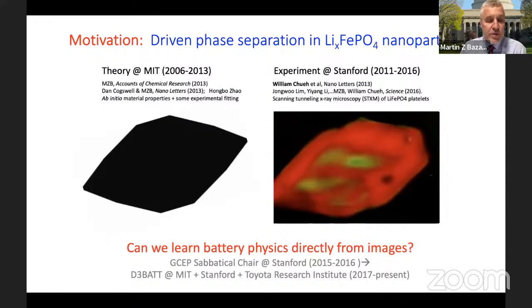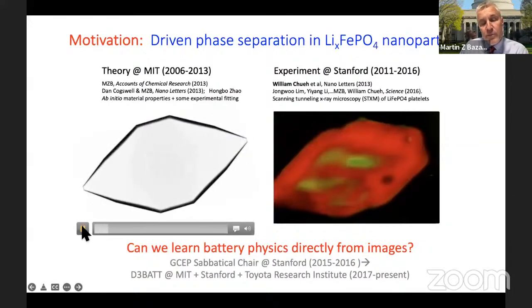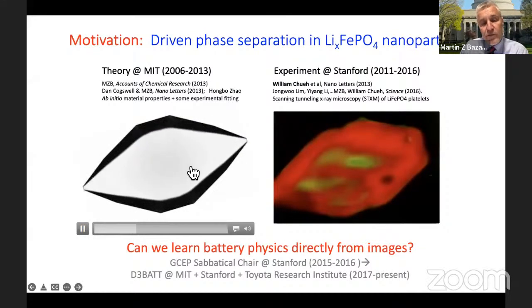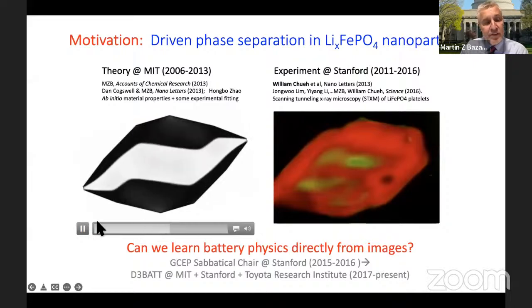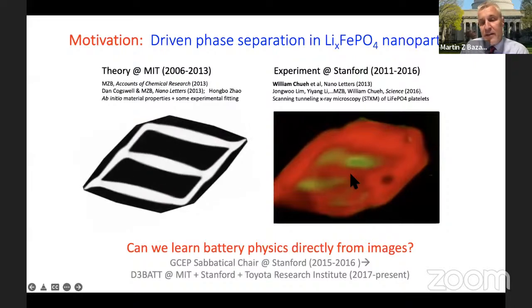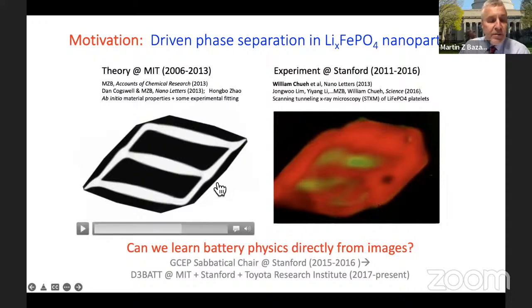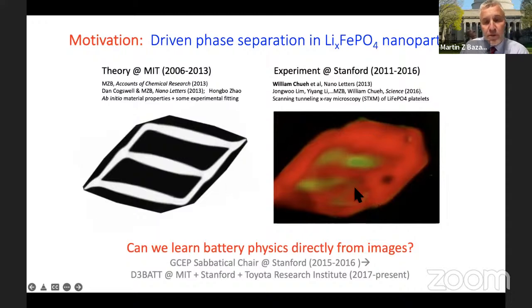And this led to this idea, well, could we actually start directly from the images and learn? Because it turns out that what we observed was pretty close to dynamics we had already predicted. In fact, if you freeze it right there, it looks pretty similar. I was actually blown away by this. I wasn't even expecting that. But if you look closely at the particle on the right, it's pretty complicated. On the left, you have an ideal crystal shape. On the right, it's more irregular. This black spot is actually a hole in the particle. So some of these particles are fractured. So it's sort of a messy system.